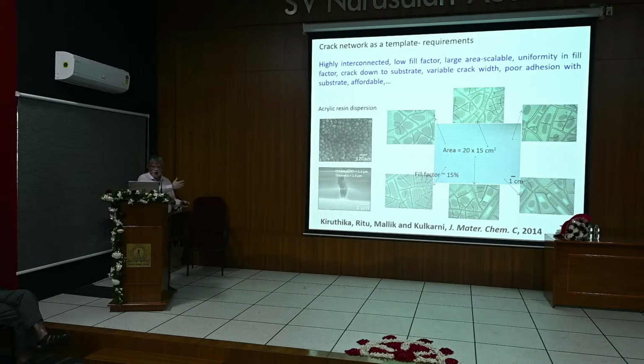Why I'm talking so much about these cracks? Because these cracks, the whole thing works like a stencil for us. We're all familiar with stencils, right? So if I take a paint now and spray on top, if you don't disturb the system, you will have the paint enter only in the crack regions. Then I can wash away the sacrificial template. What will be left behind will be the footprint of those cracks because paint entered only there.